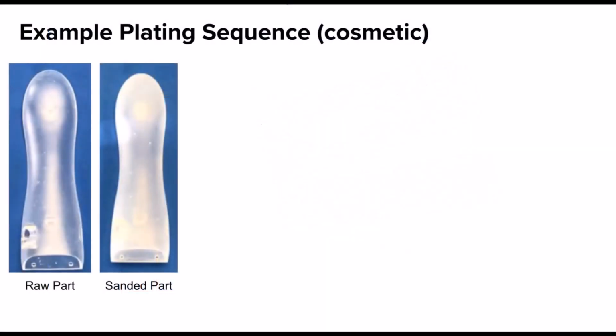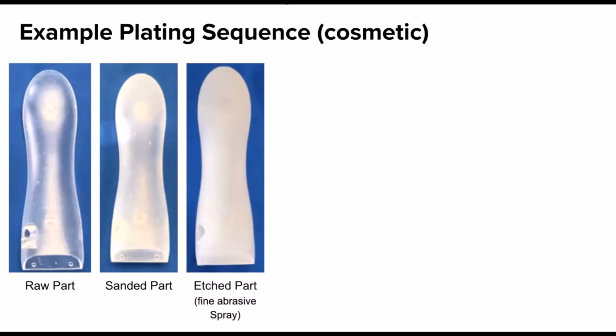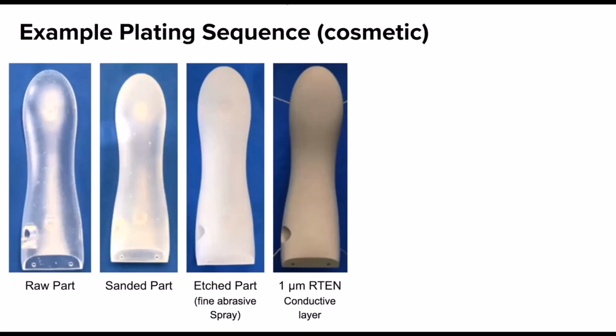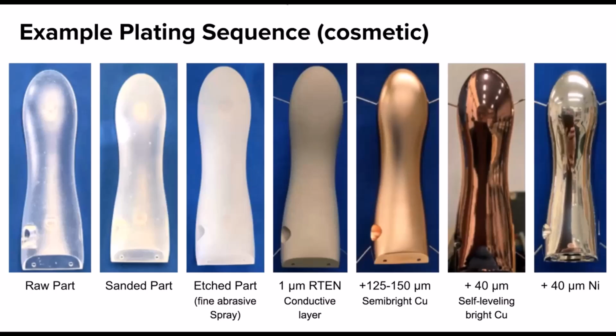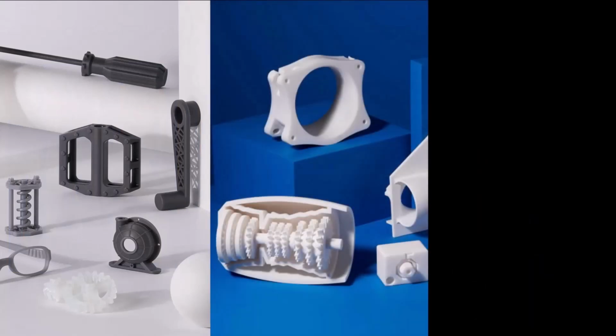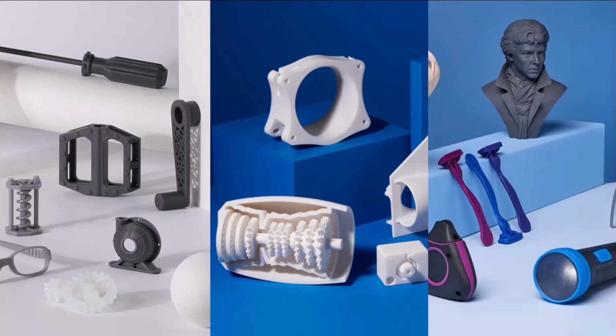Repliform's process involves reception of the lightly post-processed resin part from you, upon which they conduct an inspection. They then etch the part via media blasting to boost adhesion promotion, just like we saw with Cerakoting. Afterwards, the part experiences submersion in a room temperature electroless nickel solution to create a conductive coating for the electroplating steps. Finally, the part undergoes 1 or 2 electroplating steps for copper and nickel each, depending on the part's application. Here you can see the usual process for a cosmetic part. There's a final review after curing, and then the part is shipped back to you. Most of Formlabs resins are capable of being electroplated, but the tough, rigid, and general purpose resins perform especially well.